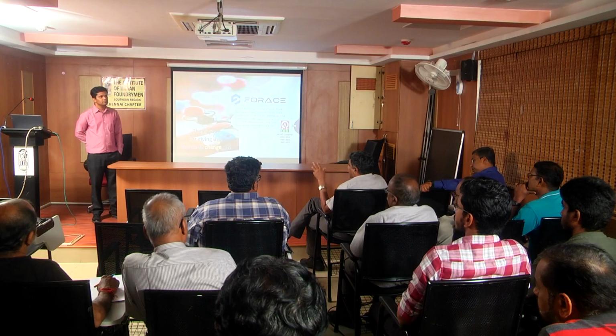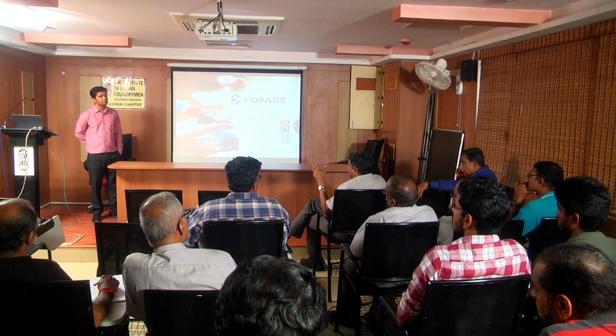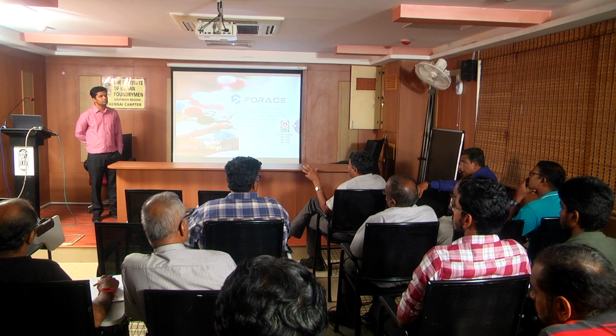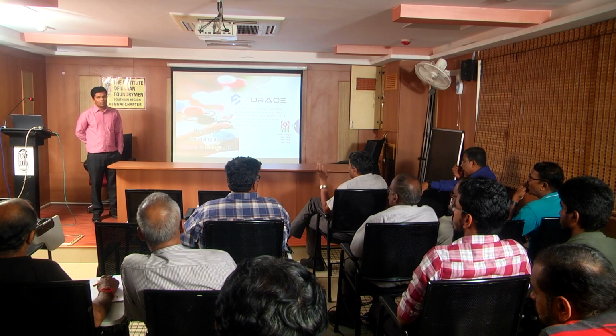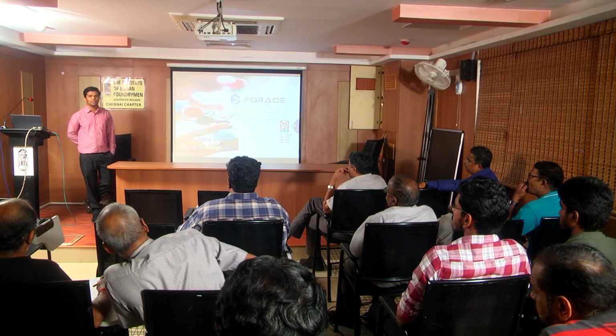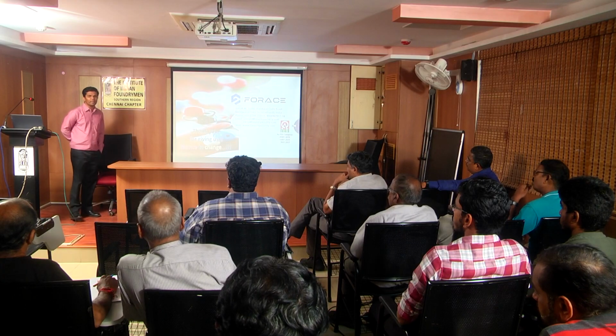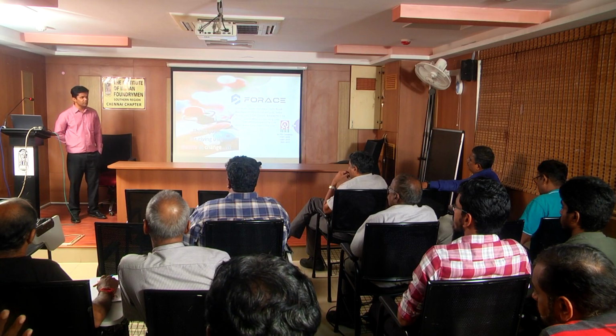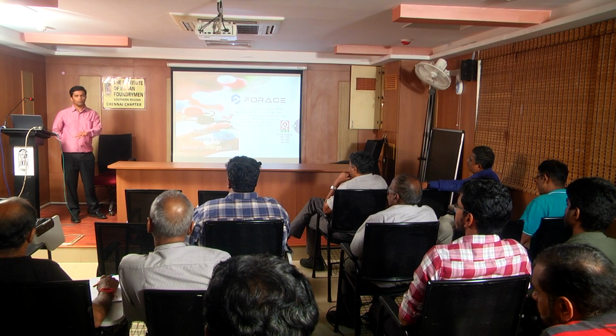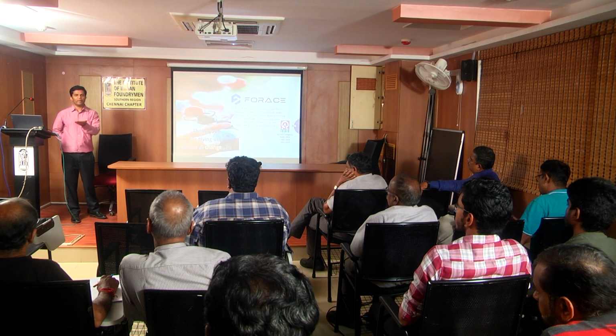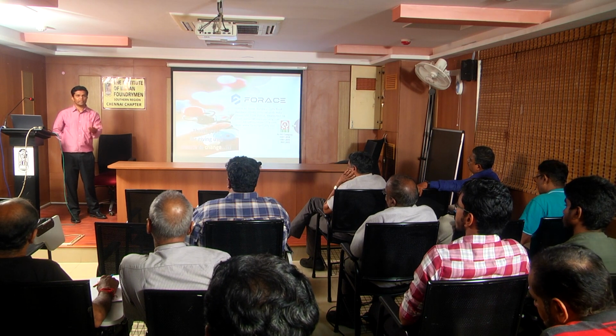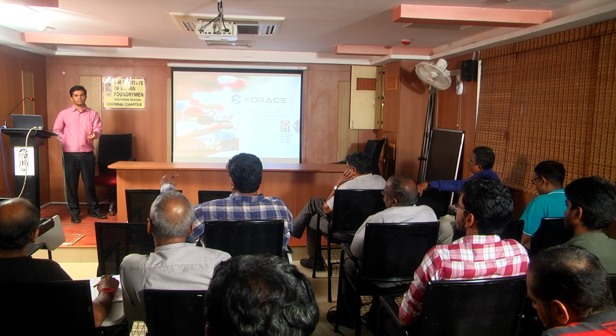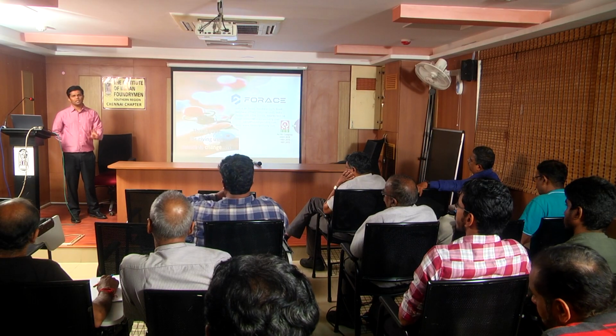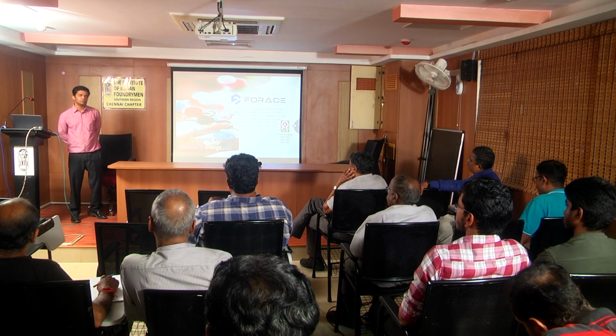Can you differentiate the insulating sleeves and exothermic sleeves, and also their application? Where have you used exothermic, where have you used insulating? Mostly for ductile iron casting, it is always recommended to use insulating sleeves. But you can go with the exothermic sleeve with some barrier in between the exothermic sleeve and the casting to avoid contamination between the sleeve and the casting surface. And for steel casting, it's always better to go for the exothermic sleeves.